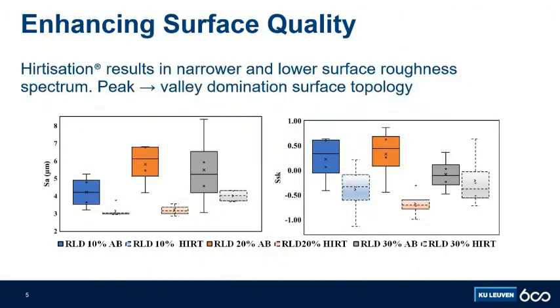Now, regarding Hirtisation and enhancing surface quality, from the entire spectrum of surface roughness parameters, I chose to show you the average surface roughness on the left and the skewness on the right. What we can observe here is, for instance, the blue is for the relative lattice density 10% before and after the treatment, sitting next to each other, side by side. The orange one is for the relative lattice density 20%, and the gray is for the relative lattice density 30%, as shown by the legend. So what we can observe is that, indeed, the interquartile ranges, minimum, maximum, and outliers have been thoroughly reduced.